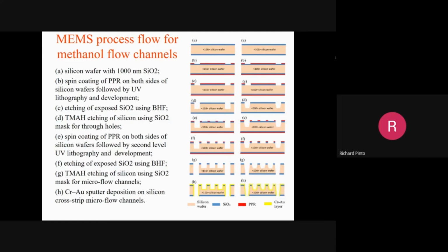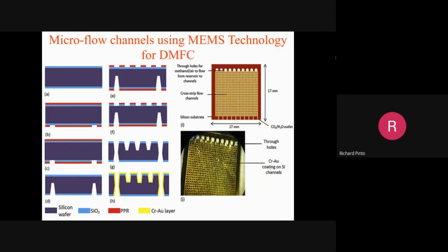Now, if you use 110, you get a rectangular profile. But if you use 100, you get a tapered profile. You see on the right side is the tapered. You'll see a better picture in the next slide. Let's go to the next slide. You see a more clear picture. This doesn't give many details, but gives the final result. This is essentially a 100 surface. You see the tapered profile, and you have the through hole here and the micro channels.